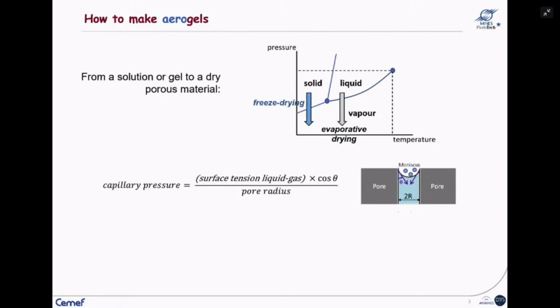There are two ways to do it: freeze drying or lyophilization, where you freeze the liquid in the pores and then sublimate it, usually done with water. Or it is possible to do drying in supercritical conditions, where you increase pressure and temperature above the critical point. In this supercritical state, the substance is neither liquid nor gas. It is very diffusive, with densities between those of the liquid and the gas. And the main thing is that there is no surface tension between the liquid and the gas. So theoretically, in this case, the capillary pressure is zero.